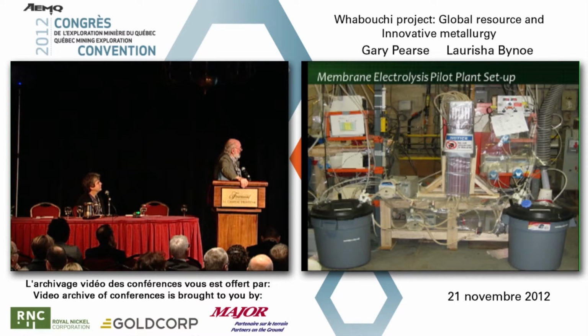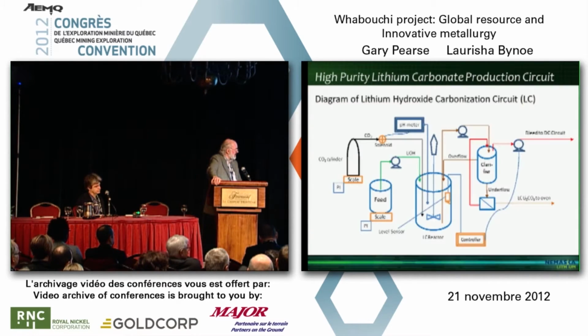And this is how it looks in the laboratory. This is a set. The three compartments can be replicated, so you end up with a battery of these, and they're very narrow spaced. And in the actual technology itself, each compartment is only about 2 millimeters wide, because the efficiency of the process in its use of electricity depends on how short a distance these ions have to move. And so you don't want to use up a whole lot of electricity heating up the solution with these ions having to make a long journey through. So it's quite a remarkable thing to see so much solution come through compartments that are only 2 millimeters in diameter.